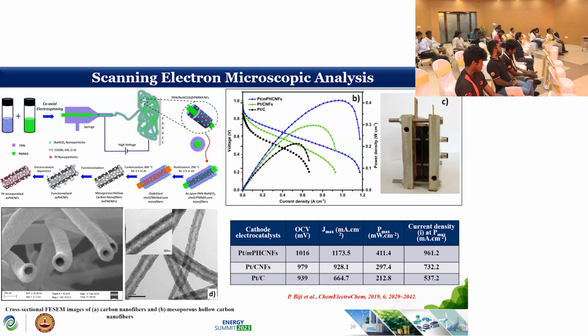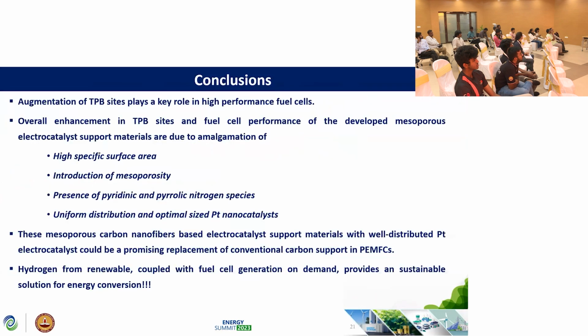So we could get the mesoporous structure again with the hollow carbon nanofibers, and effectively we could improve the distribution of platinum electrocatalyst on the surface of these carbon nanofibers. So this material also could improve the performance in a similar trend, not much variation compared to the normal mesoporous carbon nanofibers.